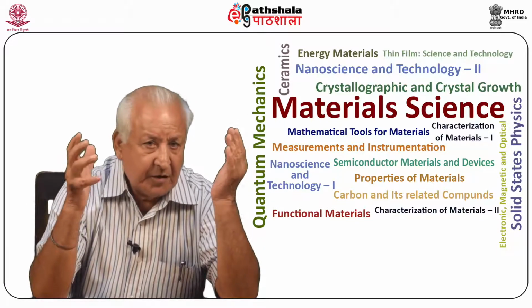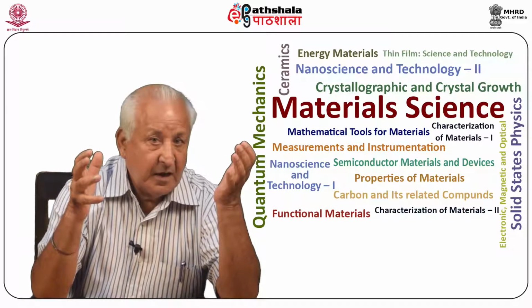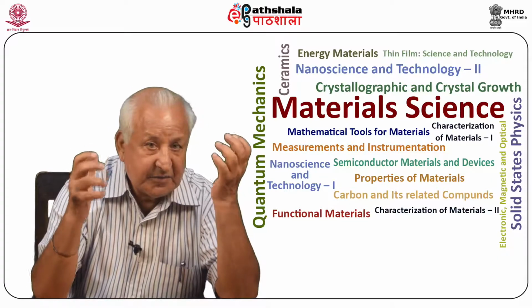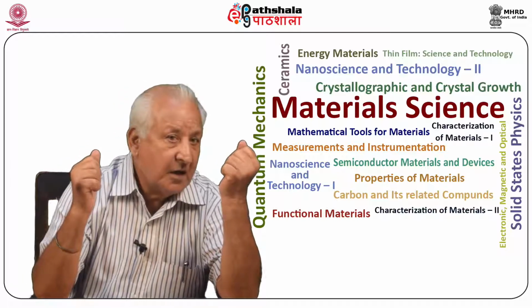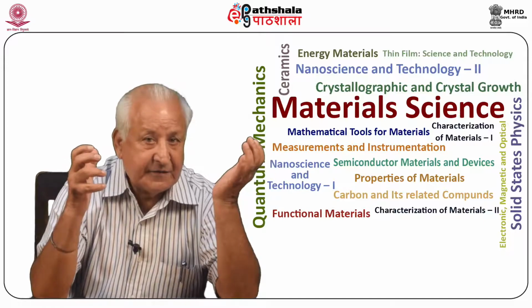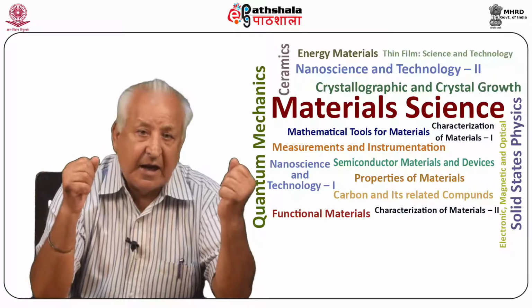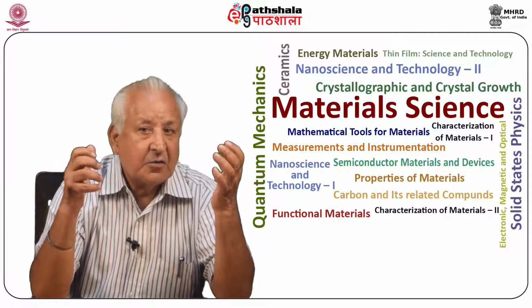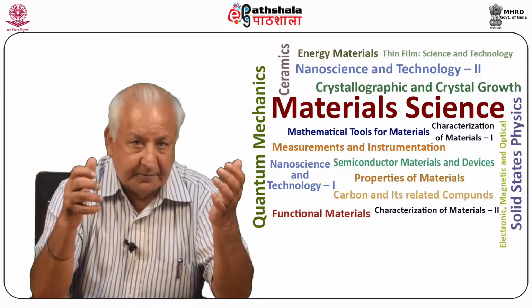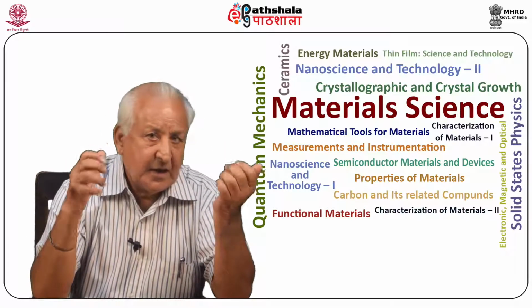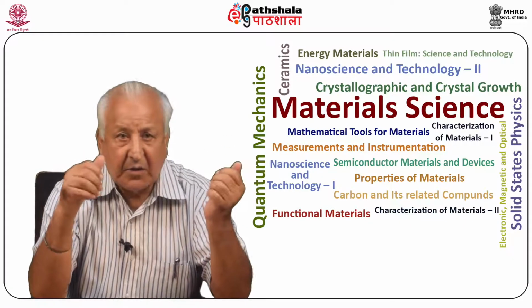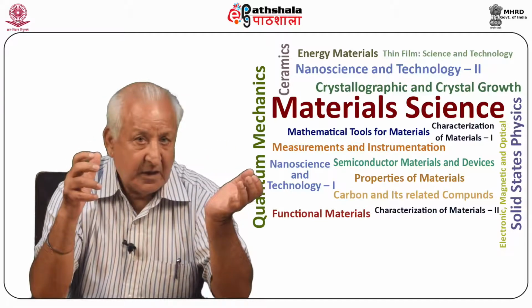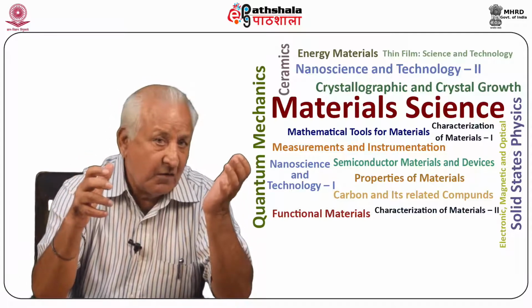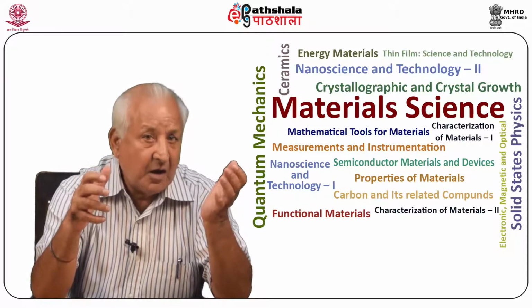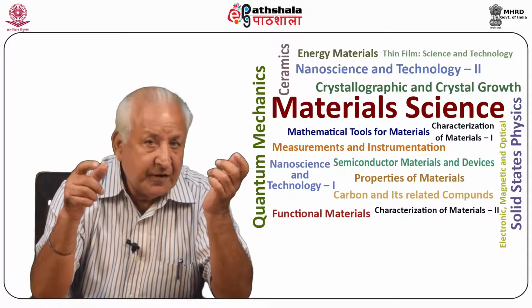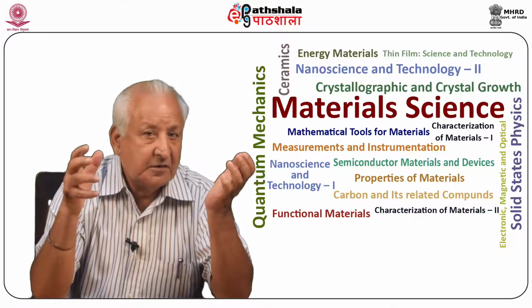During our discussion on reciprocal lattice, it has been established that crystal lattices and reciprocal lattices are related through equations 12.9 to 12.11 of section 12.2 and 12.38 to 12.40 of section 12.4 in module 12. While the crystal lattice is a lattice in real space, the reciprocal lattice is a lattice in Fourier space, which is governed by the equation exponential of i G dot r is equal to 1, which is given as equation 13.1, where G stands for the reciprocal lattice vector.